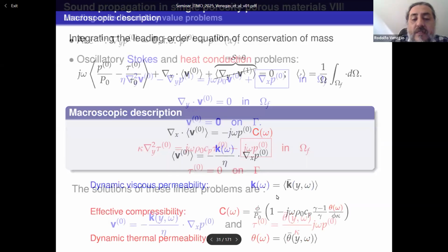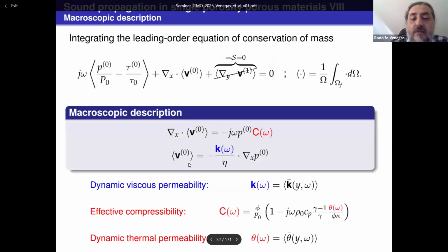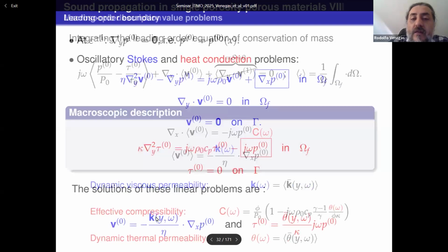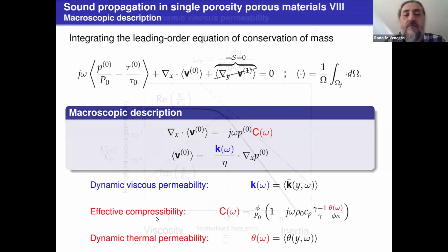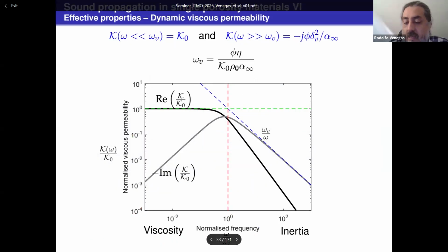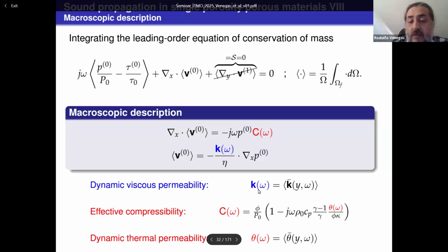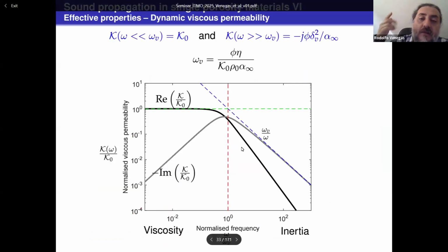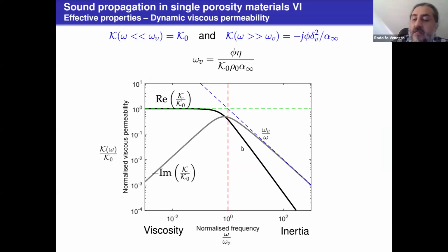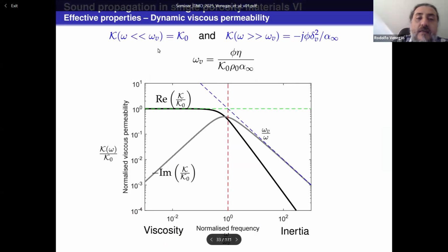And in a similar way, we take this solution, we take the spatial average, and we get Darcy's law, where K is the dynamic viscous permeability and is the average of this local operator. So that's the conventional porous materials. The properties, if we consider isotropic media, because in general this is a second rank tensor, or a particular flow direction, we get that the dynamic viscous permeability becomes a scalar, and this scalar permeability tends to its static value, which is the value for when frequency tends to 0.